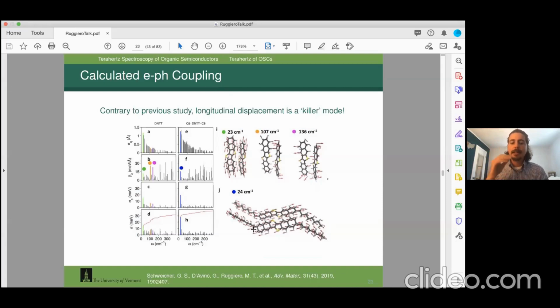The theory was that alkylation hindered that motion, and that's why it led to larger charge carrier mobility. What we found was that actually that's not true. The thing that actually helps is what you see in these 2 modes: a torsion of the semiconducting core. That torsion plays a significant role in the unalkylated system and contributes quite strongly to the overall detrimental interactions. What alkylation actually does is shift the frequency of those torsional modes to higher energies.